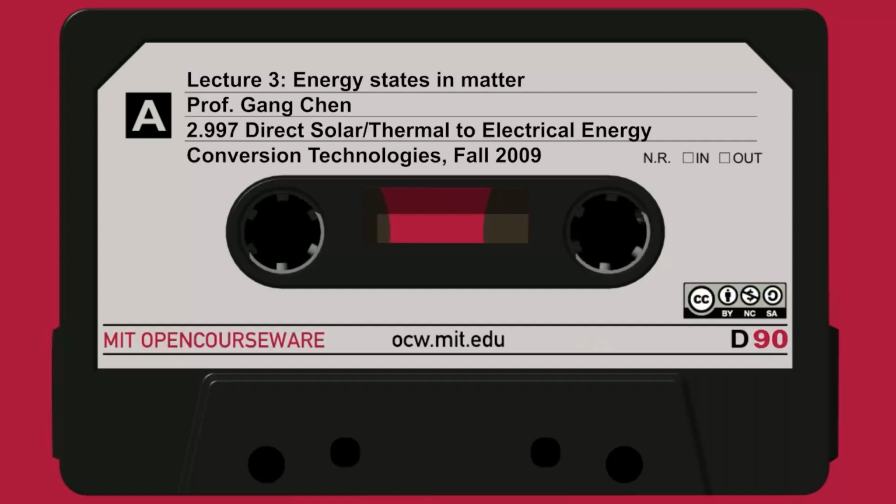A photon, the wave vector, the wavelength is about 1 micron, right? Let's think about visible light, half micron. The wave vector of the photon is 2π over λ, 2π over half micron. And here is 2π over a, where a is the lattice constant, a few angstrom.